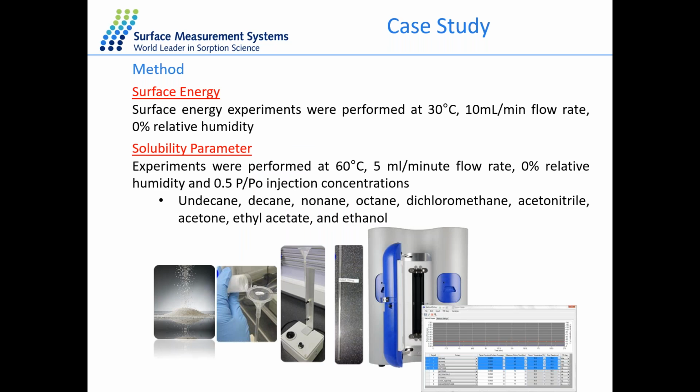For this experiment, we've carried out at 30 degrees, 10 milliliters per minute flow rate and no relative humidity. We've also carried out some solubility experiments, and this was carried out at 60 degrees, and we're injecting just the one concentration. And these are the non-polar and polar probes that we used for the experiments.